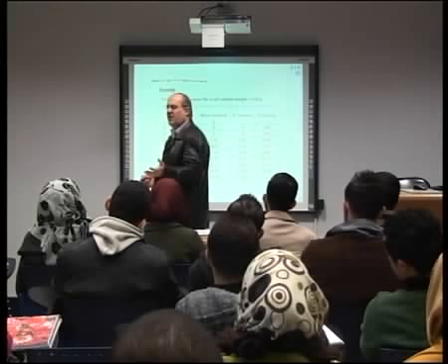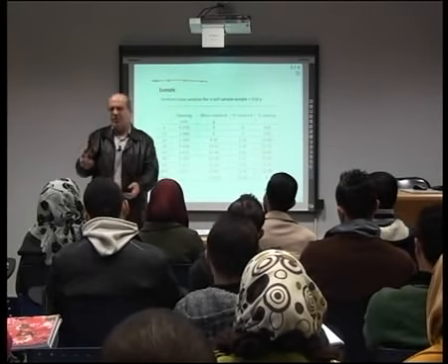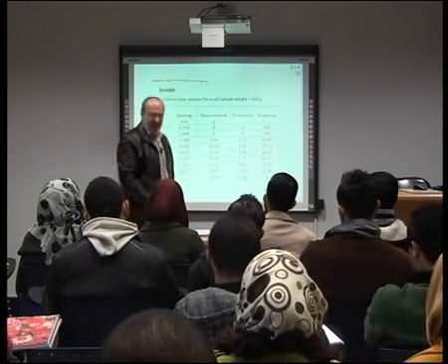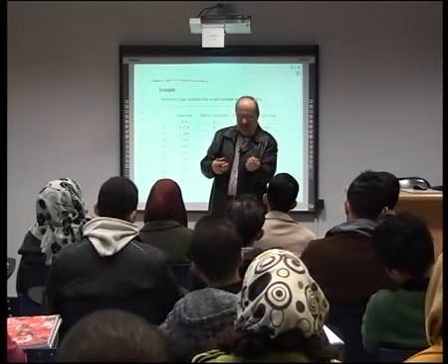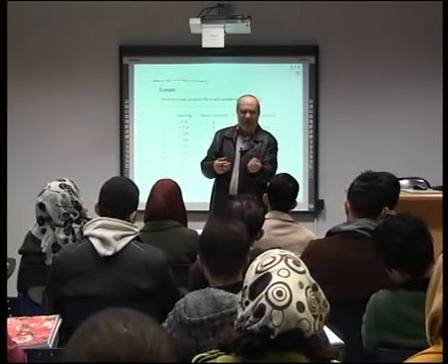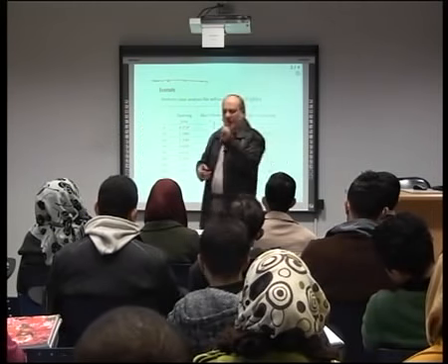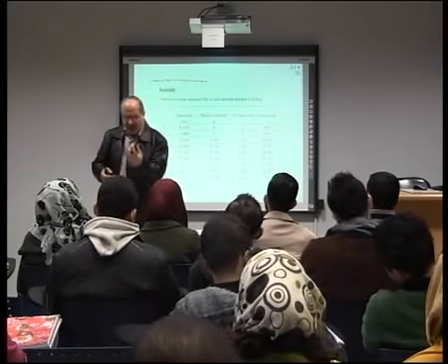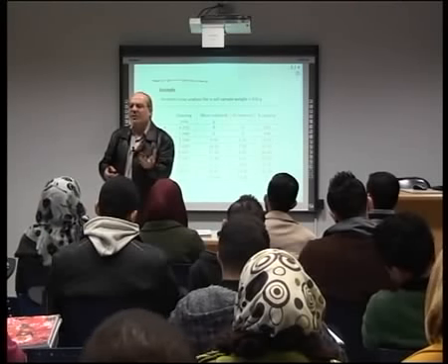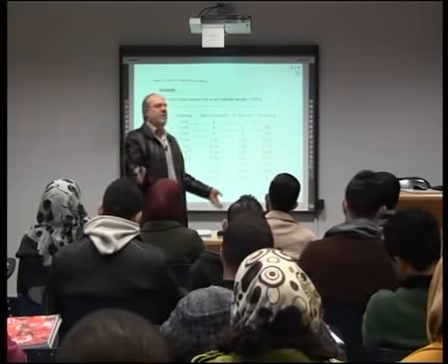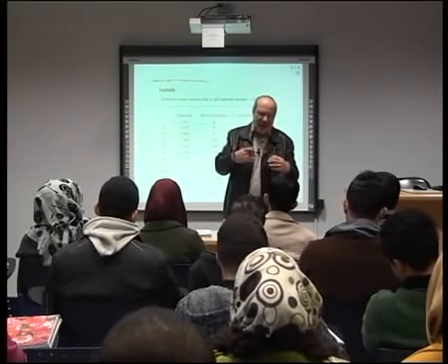If I am dealing with sand or gravel, I see that the sample is sand and gravel, maybe 2 minutes are enough. Okay? But if I'm dealing with what seems to be clay, maybe I need half an hour. Okay? The objective is to get the result of shaking. It's not to be limited to a time. It's not just, okay, 10 minutes, enough. No. It's, did we reach the objective?